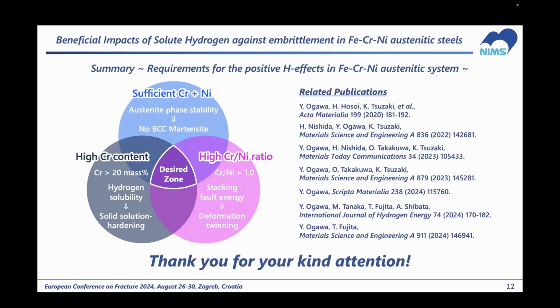So yeah, here I summarize my talk with a few important conclusions. In summary, we find a positive hydrogen effect in austenitic stainless steels with the suppression of martensitic transformations, and the requirements for the onset of such an effect are high chromium content and high chromium-nickel ratios. The former is related to the solubility of hydrogen, which enhances the solid solution hardening, and the latter requirement is related to deformation twinning based on the stacking fault energies.